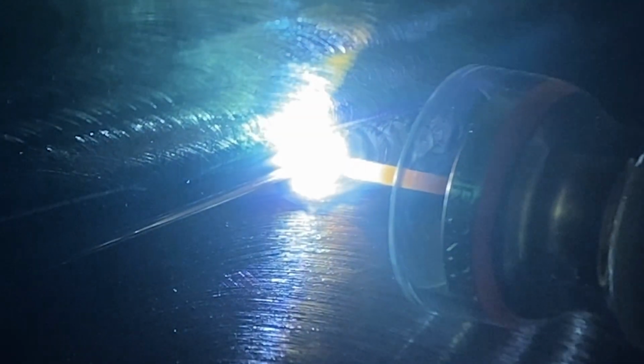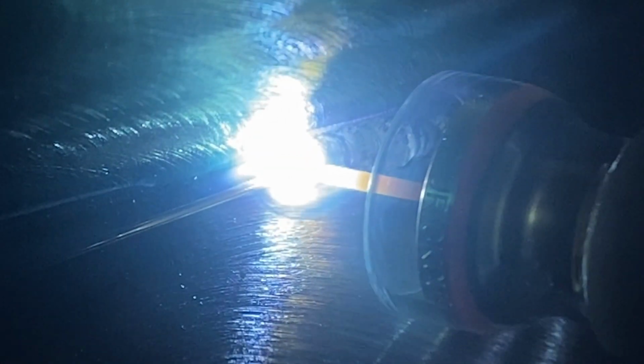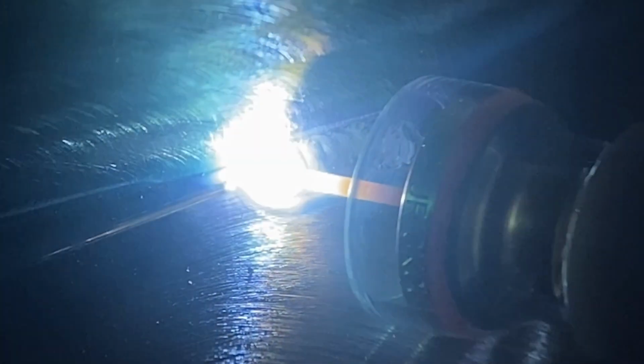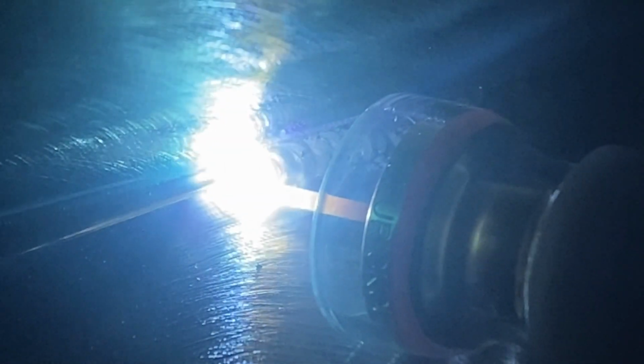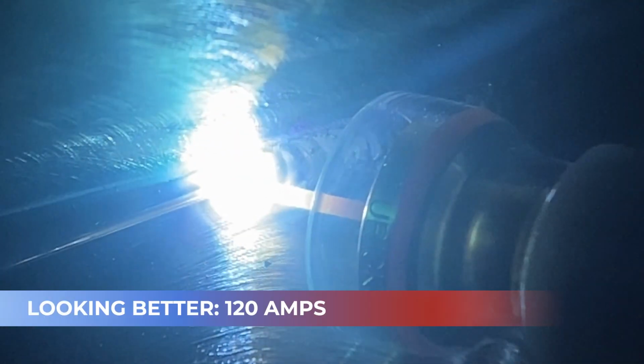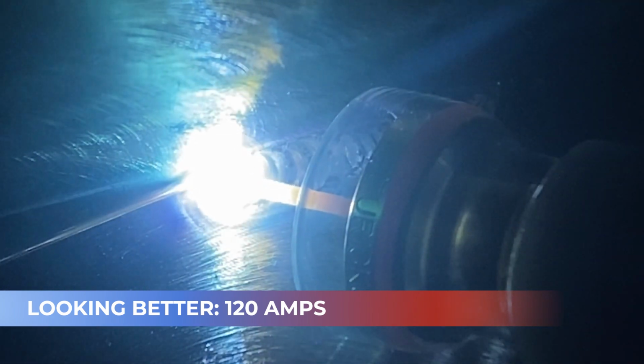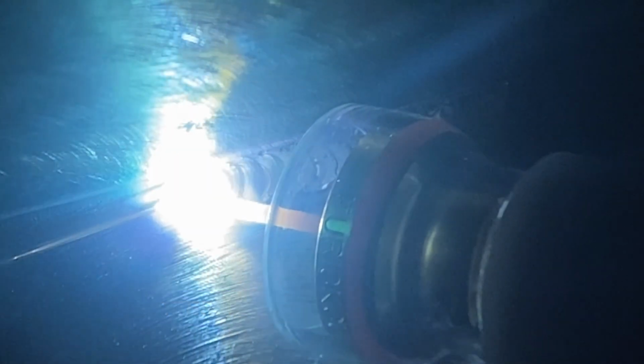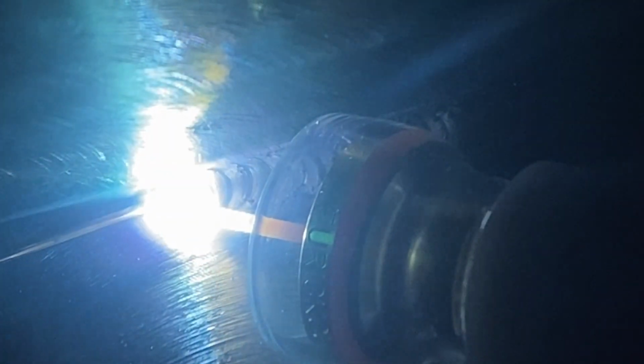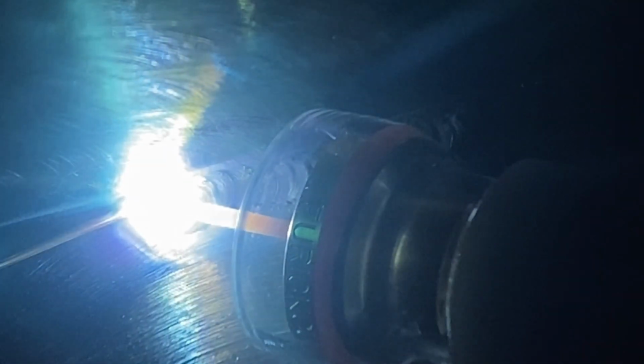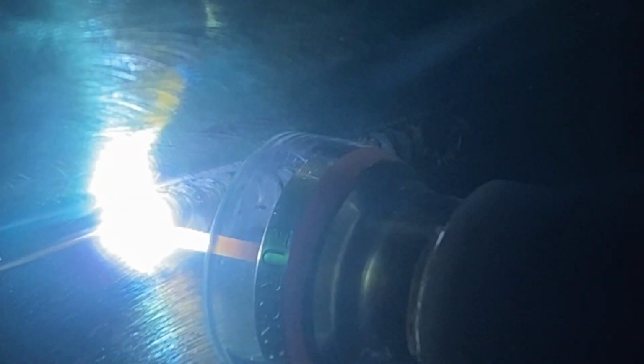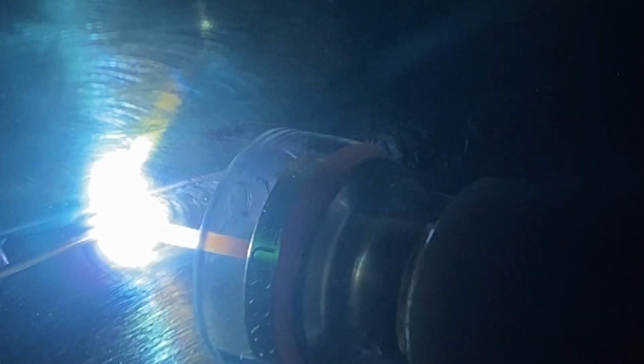So here I've reacted accordingly based on what my puddle's telling me to do, right? We found out it's too cold, found out it's too hot. I've turned it down. I'm running 120 amps on this same 12 gauge, and it looks better. You can tell right away that the puddle's not wandering. I'm able to control it. I'm getting good base metal fusion. I'm able to feed my wire, but I'm noticing that I'm pulling a lot of trash into the weld. That's because this particular piece I did not clean, to show you what happens even when your amperage is right, travel speed's right, but you're not properly cleaning your material, the result that is going to happen.